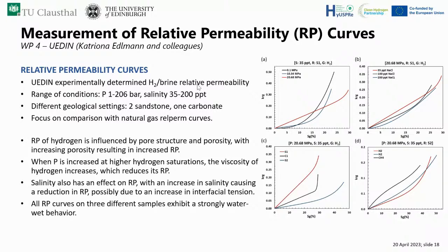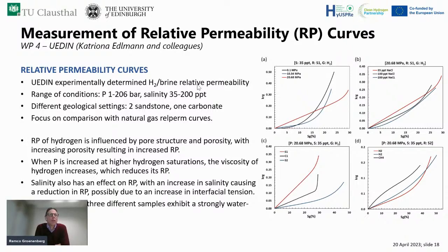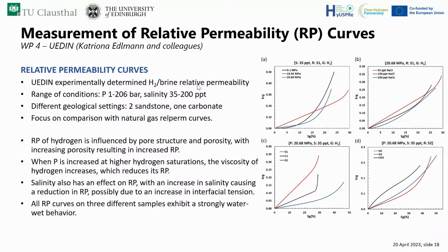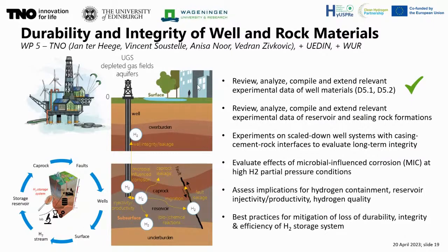At higher hydrogen saturations, when pressure is increased, the viscosity of hydrogen also increases, which reduces relative permeability. And salinity also has an effect on relative permeability, with an increase in salinity causing a reduction in relative permeability, possibly due to an increase in interfacial tension. In all cases, a strong water-wet behavior was observed for the different samples with respect to the relative permeability curves. So, results from Edinburgh. Moving on to work package 5, durability and integrity of well and rock materials.